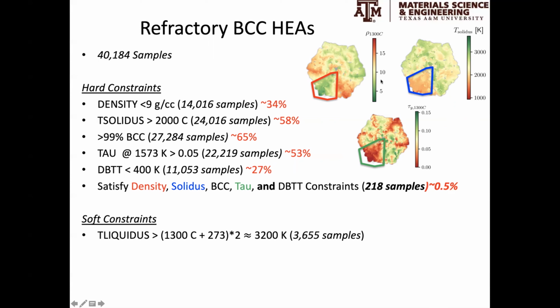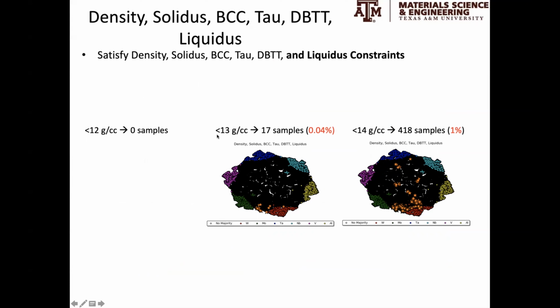On the other hand, perhaps one of the most active constraints is the liquidus constraint. When we apply this constraint, virtually no sample or alloy with less than 13 grams per cubic centimeter satisfies it. And even if we were to relax the constraint to 14 grams per cubic centimeter, only a very tiny percentage of the alloy space is satisfactory.